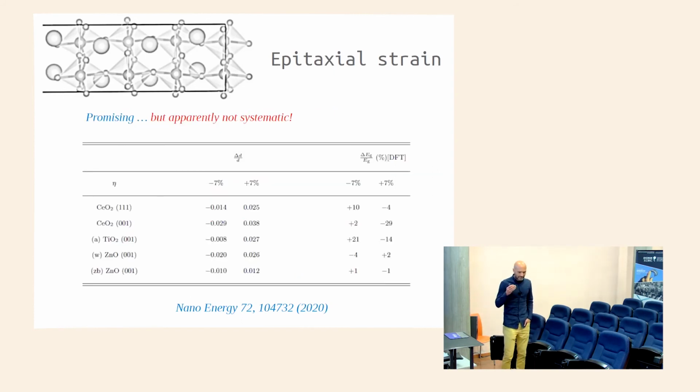The typical theory that had been used before to explain these changes in the energy band gap is, well, this table summarizes the results for maximum tensile biaxial stress and maximum compressive biaxial stress. This is the relative change in the energy band gap, right? Before us, people were trying to understand these changes in terms of the deformation potential theory, which basically has to do with how the overlap between the oxygen p orbitals and the d or f orbitals from the transition metals is affected by changing the structure by applying stress, right? Essentially, in that theory, when you put the atoms closer, somehow you are increasing the overlap between these